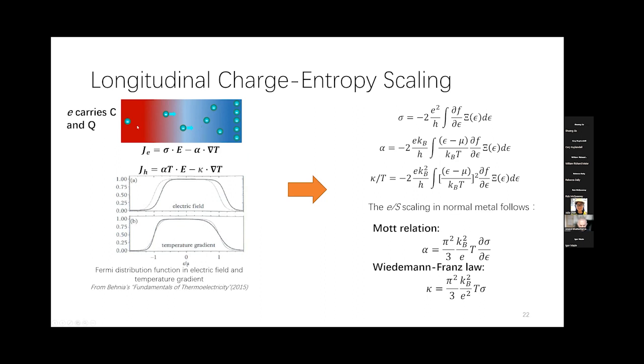So what is the difference for the electrons inside a temperature gradient and an electric field? Basically, with the electric field, you just shift the Fermi distribution function by a small energy. Or for a temperature gradient, you just change the shape of the Fermi surface. So that's the reason if you calculate the thermal conductivity and the electrical conductivity, you need to consider a transport distribution function times the derivative of the Fermi distribution function with respect to energy for the conductivity. Or for alpha, you need to multiply by the derivative of the Fermi distribution with respect to temperature, which equals the derivative of the Fermi distribution with respect to energy times (E minus mu) over T. So this is a large difference. And at low temperature, you will see the Mott relation and the Wiedemann-Franz law.